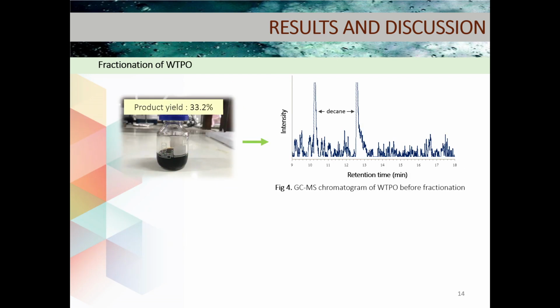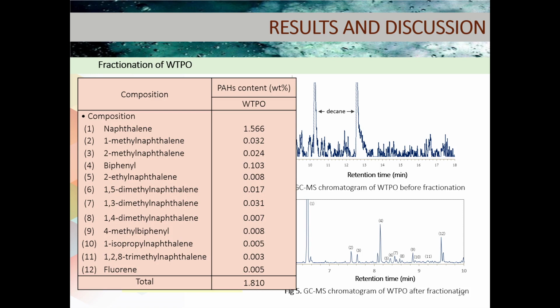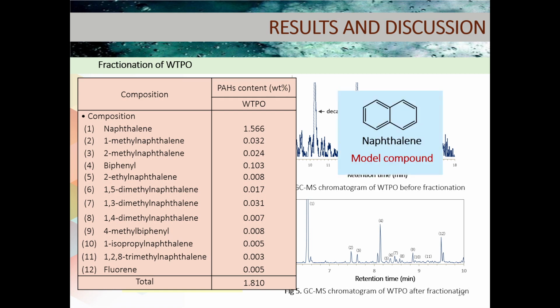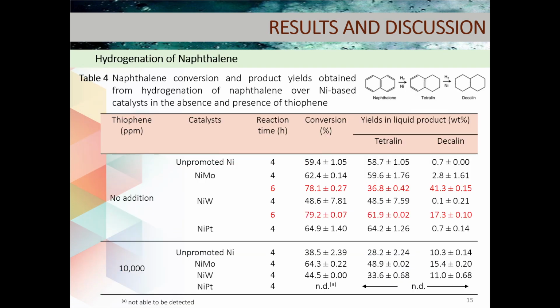And to see the identification of the WTPO, you can observe that after we use the GC-MS and the fractionation, the WTPO shows a high amount of naphthalene and its derivatives. So in the next step, we use the naphthalene as the model compound for the hydrogenation to screen the catalyst. And this table shows that after we add the catalyst into the system, the nickel molybdenum, nickel tungsten, and nickel platinum can show a percent conversion of the naphthalene of about